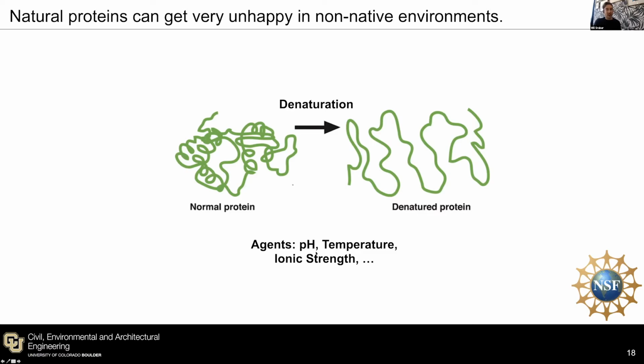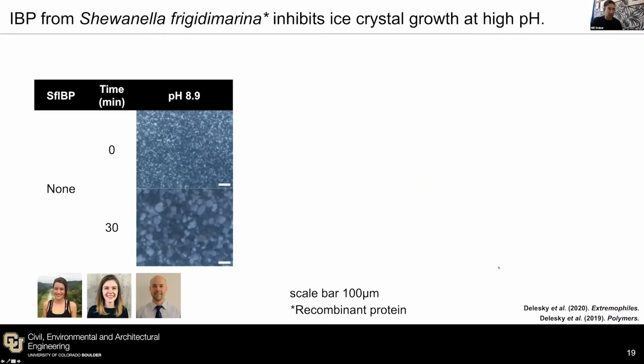If you know anything about concrete, you know that if you squeeze concrete and a drop of liquid comes out, the pH of that solution is about 12.5 to 13. It's very, very basic, high ionic strength. And so, we thought, well, proteins probably won't be very happy in that environment, but we tested it anyway.